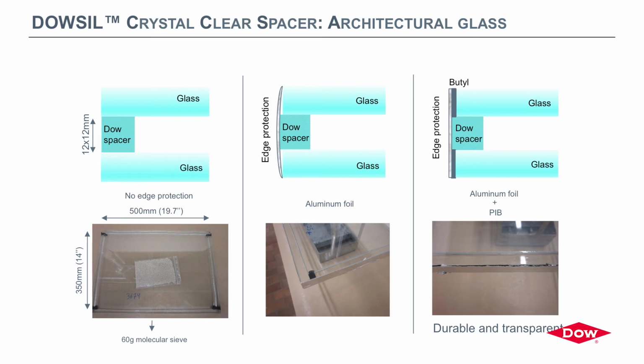So we've been playing around in the lab since quite some time now, evaluating different concepts. Here you can see the first setup with just the Dow spacer. We realize, of course, that this one is not going to be very durable. It's acting as a reference. There is no primary seal. You can see here that we are assembling 4 pieces of the spacer together with just a conventional black silicone gun grade, what we had in the lab. You could easily assemble it with different transparent solutions or have it cast in the right shape directly. You can see as well that for the moment we have an original way of integrating the desiccant. It's a plastic bag with the amount of desiccant that we need.